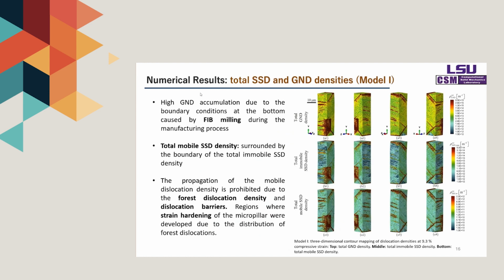Figure A1, as you can see here, for Model 1 shows the distribution of high GNDs, which is considerably influenced by boundary conditions. High GND accumulation was achieved due to the boundary conditions at the bottom caused by FIB milling during the manufacturing process.